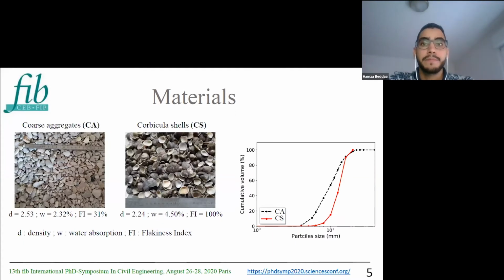So these shells are from 4 to 20 millimeters, the same granular class as coarse aggregate. So we will study the effect of the substitution of coarse aggregate by shells on the concrete properties. Comparing the properties of the shells with those of the coarse aggregate, we can say that shells contain fewer fine elements. And we can say also that the density is less for the shells, and they absorb more water than coarse aggregate.